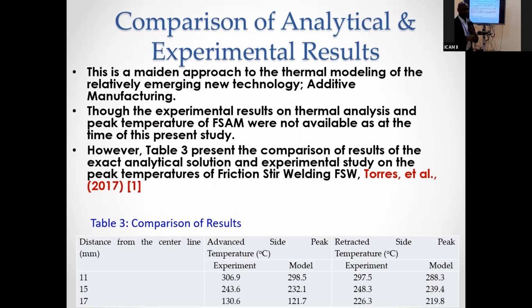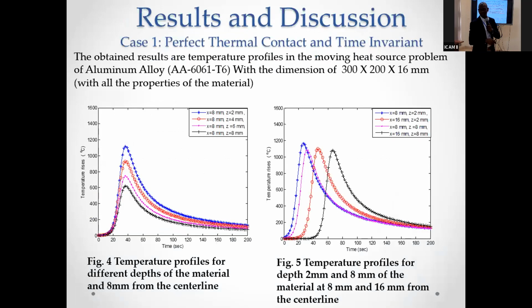Now, for this study, this is the first time we are doing it, and we've not done an experimental study on this. In order to validate our work, one thing is to develop the model, but if the model is not validated, either by a numerical method or more importantly an experimental method, you're just guessing. So what we did was to compare our results with what had been done. Somebody had done work on aluminum alloy using friction stir welding, and since our method is from friction stir, we compared our results. We discovered that our results, maybe not in perfect agreement, are in good agreement with the experiment. We picked points at 11 millimeters on the plate, 15 millimeters, and 17, and we have good agreement between the two of them.